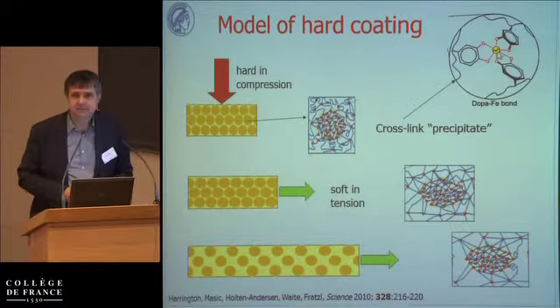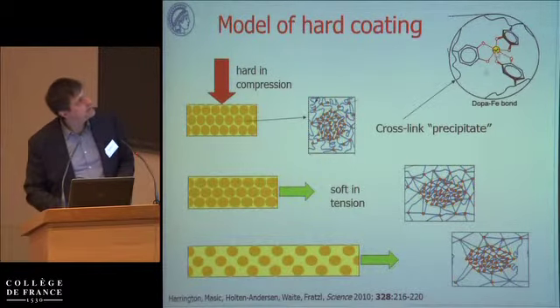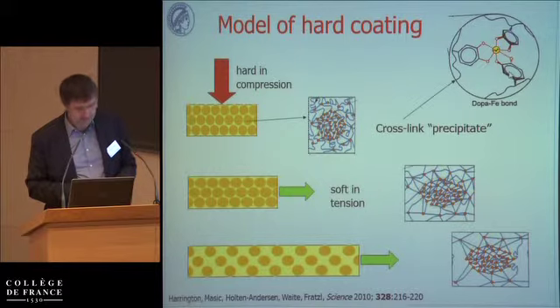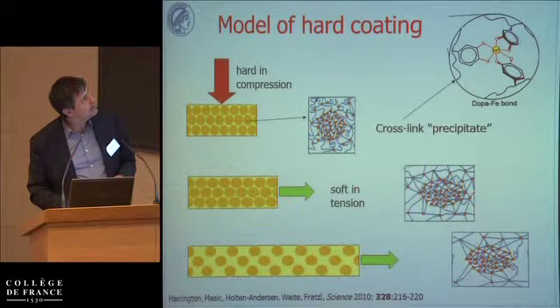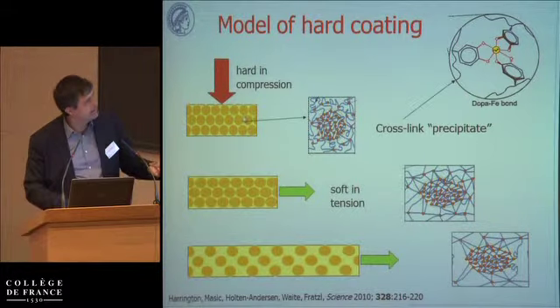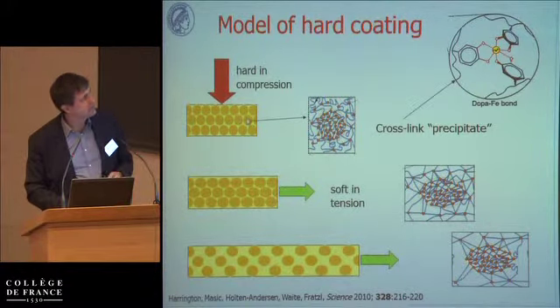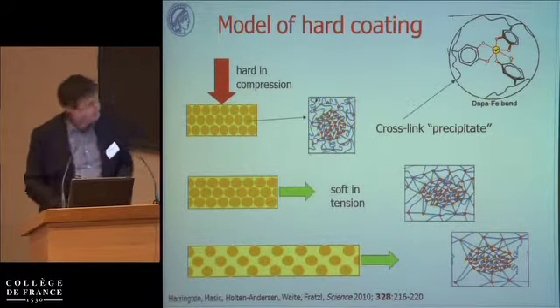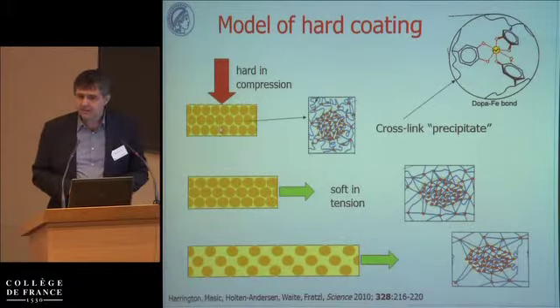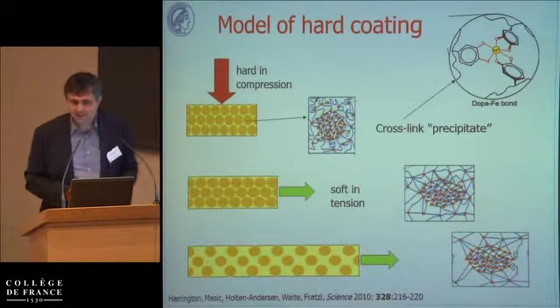This is not zinc now, this is iron that coordinates these DOPA catechol side chains of amino acids, and creates these very, very hard droplets. So they are much harder than the matrix surrounding them. It's the same protein. The dark yellow is the same protein as the light yellow. The only difference is the different cross-link densities, as schematically shown here. And now here is the trick. The trick is you have to design a material that is soft in tension but hard in compression.